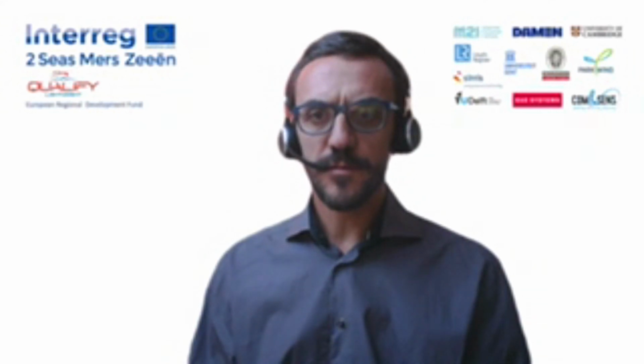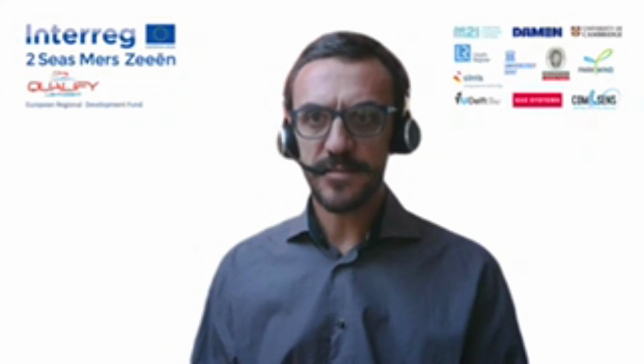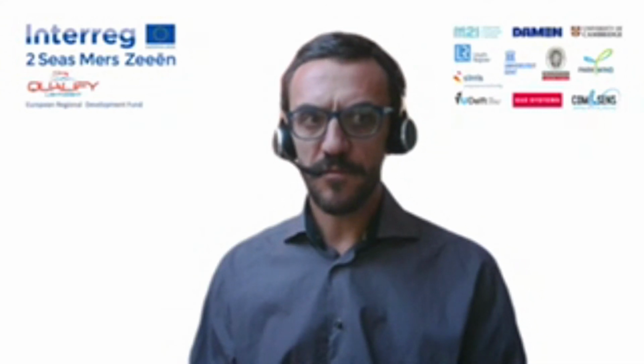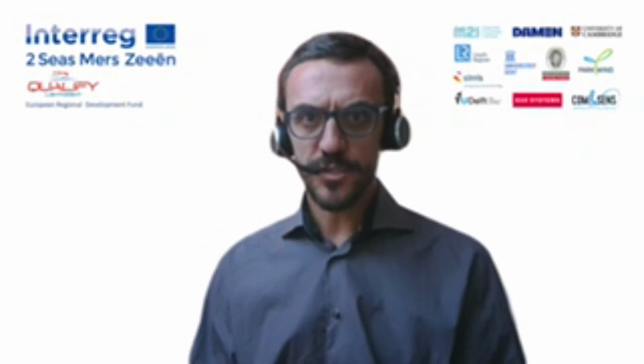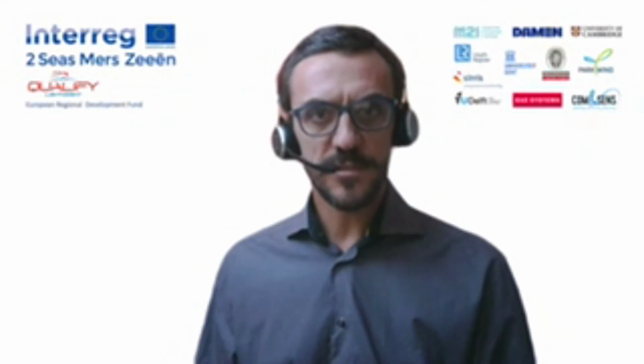I just want to note that in 2019, when we had one of the Qualify meetings, one of the people in the room asked us about this test that we were thinking of, making 5 to 7 weeks, we didn't know yet at that time, immersion test of the full-scale specimen, and at 50 degrees. And the person said, but the problem is that your test is too severe, and you should plan something in case it fails, so what kind of conclusion can you withdraw if the test fails? And I think now we are 2 years later, the test has been performed as we planned in this time.